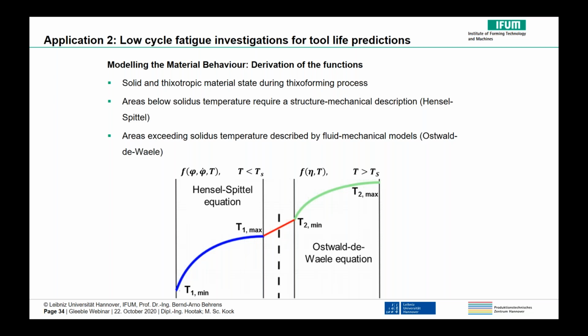During the thixoforming process, the material adopts both a solid and a thixotropic state, as different areas of the workpiece reach different temperatures. Thus, areas below the solidus temperature require a structure-mechanical description. We used, for example, the Hensel-Spittel equation, whereas the areas exceeding the solidus temperature are described by a fluid mechanical model, such as the Ostwald-de Waele approach, which we use in this work. And this relationship can be expressed, for example, by a section-wise defined function, and then it can be written as a subroutine in the FE software.